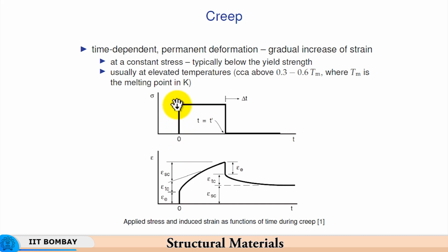Now, if you subject the material to some stress, so this sigma can be much lower than the yield strength, and then you maintain it for a sufficiently long time. So, your stress pulse is something like this: an instantaneous rise to its working stress, then hold it for a long time, and then bring it back to zero stress instantaneously. The strain response is relatively lax, in the sense it lags in terms of time. For the strain to fully develop, it takes a significant amount of time, and when you unload, again there is some instantaneous unloading. Just as you have some instantaneous strain during loading, there is an instantaneous unloading strain,